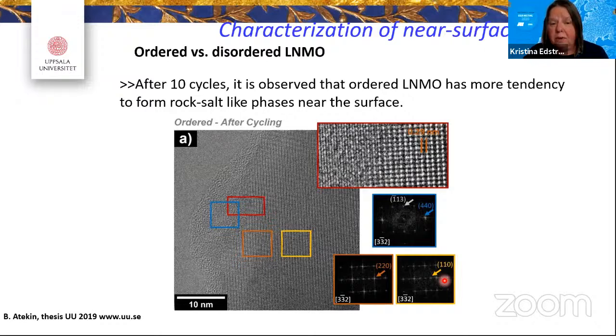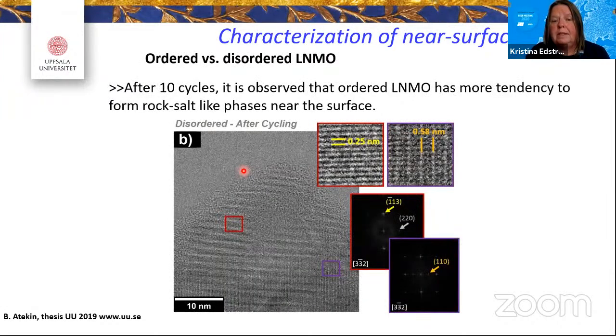And for the ordered one with the spinel structure, already quite early, after only 10 cycles, lithium out and lithium in, you get a very ordered surface structure and you have your bulk structure still as the spinel. And this is very different from the cycling of the disordered sample. So you actually induce structural changes just by doing the electrochemistry. And here you have very little formation of rock salt structure.